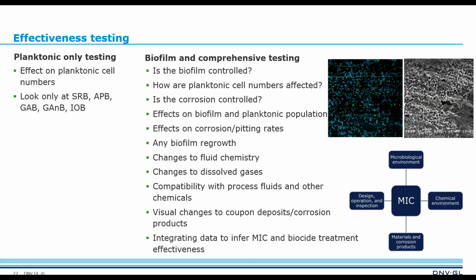Biocide effectiveness testing is the next step, and this effectiveness testing is usually done by investigating the effect on planktonic cell numbers, or by looking at how numbers of common MIC-associated species or functional groups like sulfate reducers and acid producers have changed. But because MIC is mediated by biofilms, analyzing the effects of biocides on biofilms and other parameters like corrosion rates, corrosion products, and chemical environment is important, so more comprehensive testing is recommended.